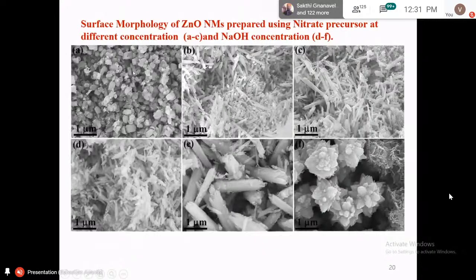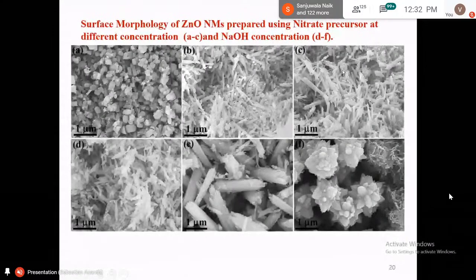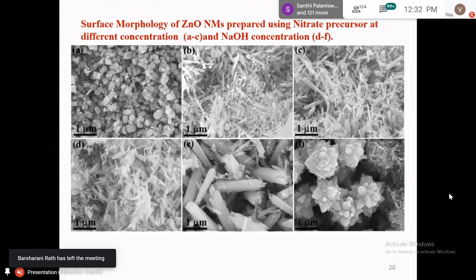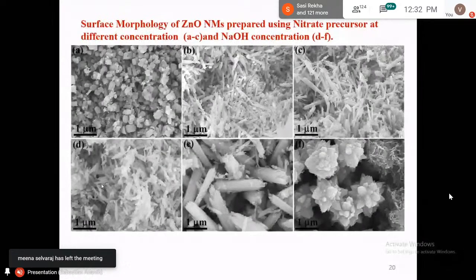Here in this range, we use different concentrations: 0.05 mole, 0.075 mole, or 0.1 mole. So first, we fix the nitrate concentration and then vary the NaOH concentration. And then second, we fix the NaOH concentration and then vary this zinc nitrate precursor concentration.